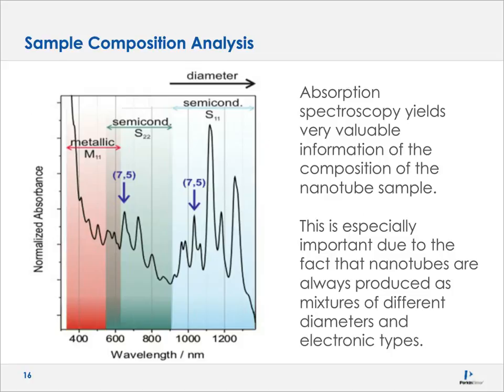The energy diagram shows the metallic transition as a high-energy transition (red), while semiconducting transitions (blue) are smaller in energy — and there are actually two semiconductor transitions typical in single-walled carbon nanotubes. In the spectra, the metallic transition is color-coded red, corresponding to shorter wavelengths of higher energy. The two semiconductor transitions occur in the 600–900 nm region for one, and the 900–1400 nm region for the other. You can identify nanotube species by which peaks appear in which region.